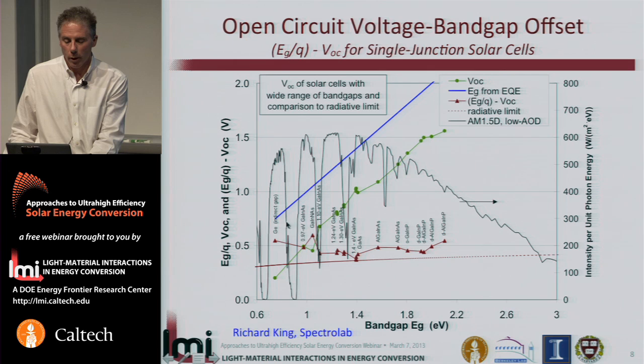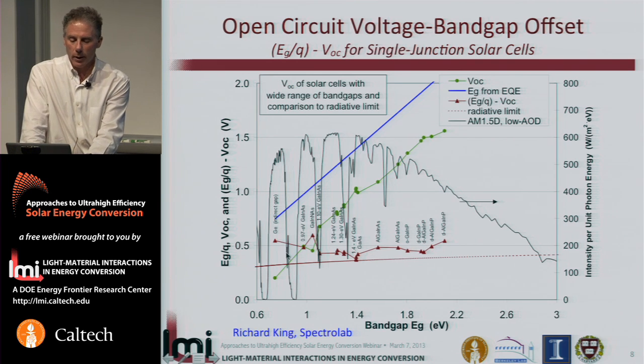And this plot shows, it's a nice plot from Richard King, my friend Richard King at Spectrolab, that shows the open circuit voltage of a solar cell here depicted with experimental points for a large number of solar cells in the compound semiconductor family between 0.6 and 2 eV. And you can see that the offset between the open circuit voltage and the band gap is almost a constant of about 400 or 500 millivolts. And this set of data here depicts the subtraction of the open circuit voltage from the band gap. And you can see that the sum of entropic terms that I was speaking about on the previous slide is in fact limiting the open circuit voltage to be less than the band gap energy by about this number, almost independent.